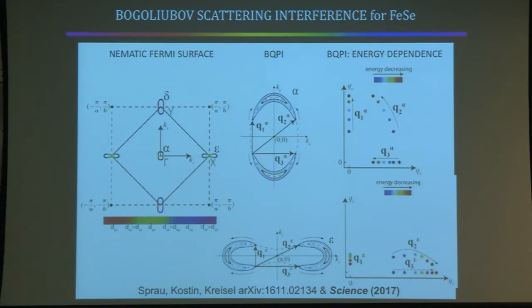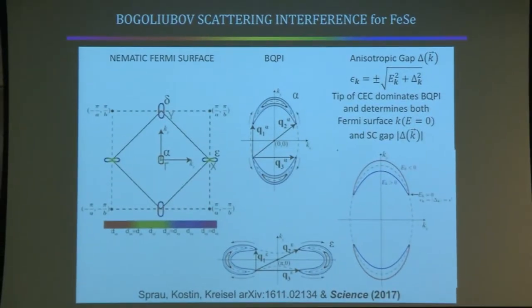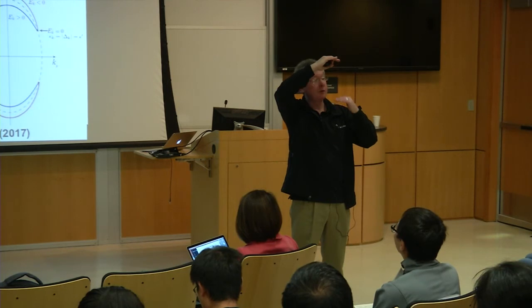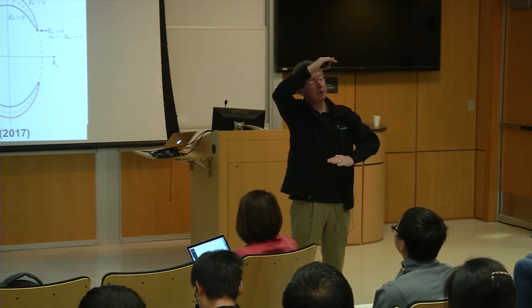I can't see through if there are degenerate states in your iron selenide. Yeah. I mean, as you fiddle the d and the orbital stuff, are there equally good degenerate solutions? Good question. So it should be from DMFT that dxy would be split, fairly strongly split, from dxz and dyz, which otherwise would be degenerate from symmetry considerations. And then the other two orbitals, the x squared minus y squared and z squared, would be far below the chemical potential.